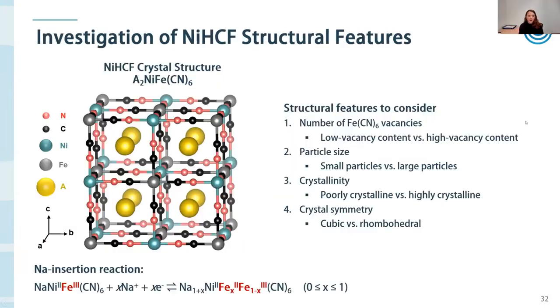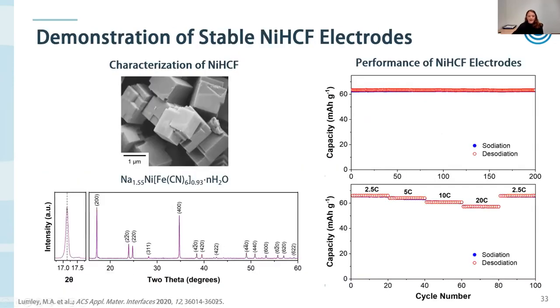And I spent a long time during my PhD investigating different structural features. One thing that I looked at is the number of ferricyanide vacancies. So you can essentially have holes in your crystal structure, which affect the performance. Also looking at particle size. So how big are the particles that we're producing? Crystallinity, and then crystal symmetry. And I won't go through all of this work. I'll kind of skip to the end, which is the good result. But if you're interested, you can take a look at this paper that I published back in 2020. The reference is at the bottom of the slide.